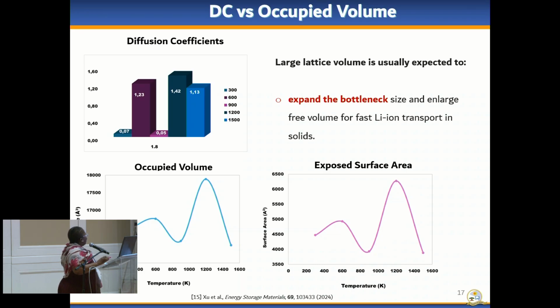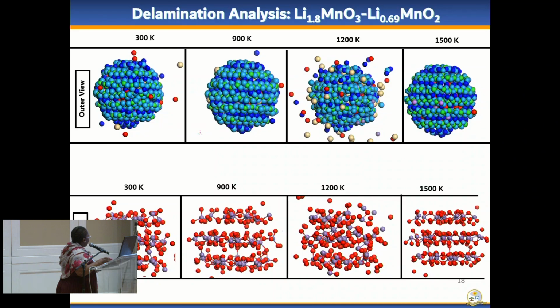We then chose a concentration to sample on, and it had to be one that has these kinds of fluctuations, because we wanted to see if there was any relationship between the trends in diffusion coefficients and the occupied volume as well as the exposed surface area of our cathode core shell material. We found that there seems to be some form of relationship, because we have a peak here and then it drops and then it goes up again. This is exactly what we're seeing with the occupied volume and the exposed surface area of our core shell material. So we opted to visualize the core shell structures at different temperatures.